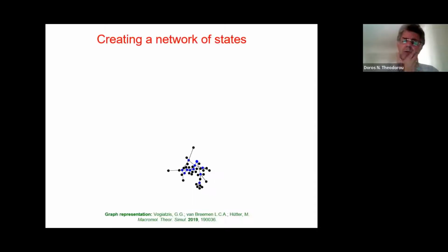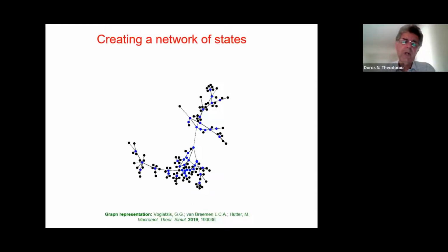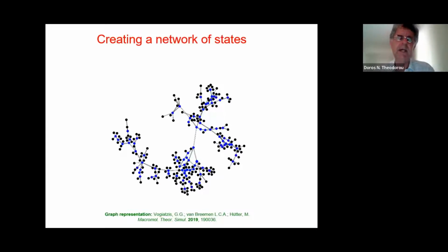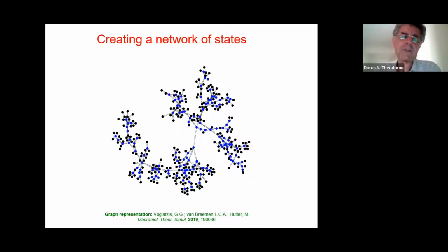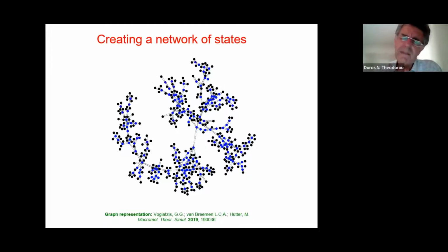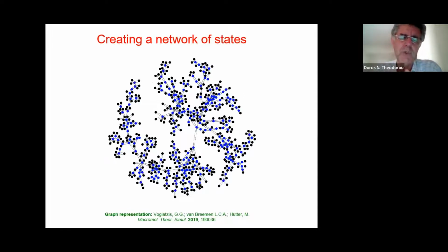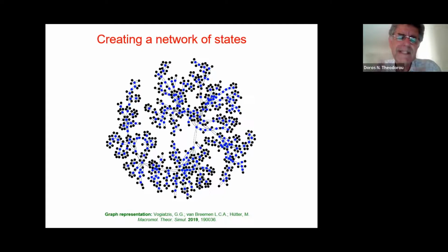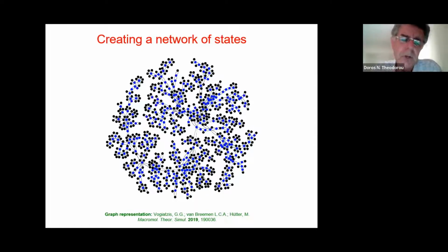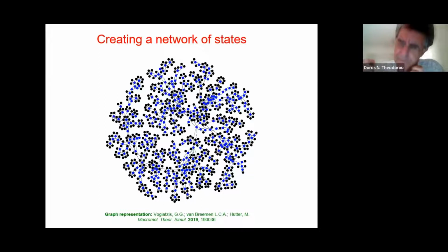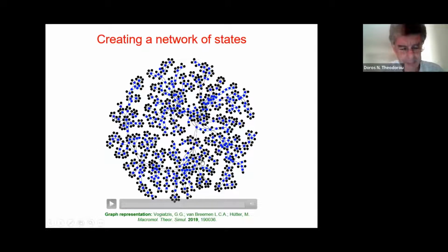So we start from a minimum, and we gradually discover more and more minima going across saddle points in configuration space. The blue dots in this graph here symbolize what we call explored minima, minima for which we have calculated as many as possible saddle points leading out of them. The black dots are boundary minima, as we call them, or boundary states. They are minima which are connected to explored states, but not yet explored themselves. And one sees that there is a very rich connectivity in multidimensional configuration space. For each pair of minima, we know the rate constants between them, which are symbolized by these double lines.